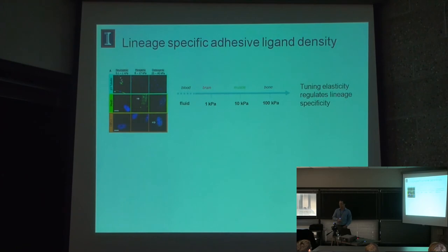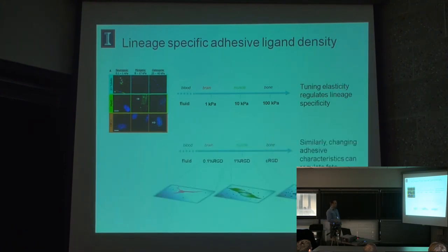So consider this example of stiffness, where people have been talking for quite a while now about the importance of the material's elasticity and its stiffness in directing differentiation. So from this work, it suggests that in addition to stiffness, we may be able to modulate the density and the affinity of ligands on the biomaterial to get similar trends in lineage specification. And I think this is interesting for a number of reasons, for a practical reason, for biomaterials design. If you want to promote bone cell fate, have a high density of cyclic peptides.